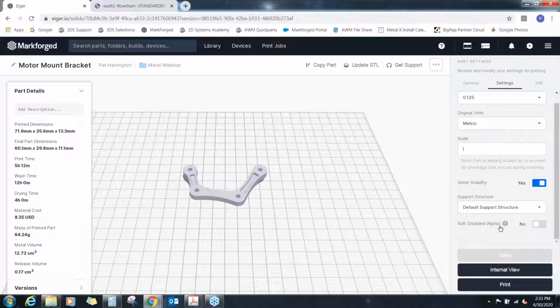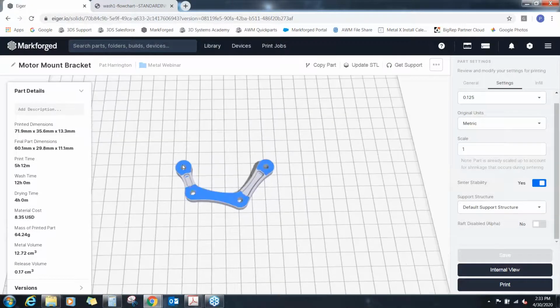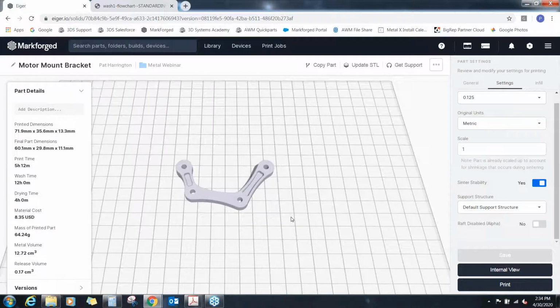But what we've found is the raft does quite a bit for making sure that the part shrinks uniformly in the sintering process. These parts shrink around their geometrical centroid, so the raft ensures that, in a part like this, you won't get uneven shrinkage in this smaller leg of the part versus this longer leg. The raft keeps the whole part kind of together so that it'll shrink more uniformly. But in certain parts and geometries, you can turn off that raft and save some material and print time.